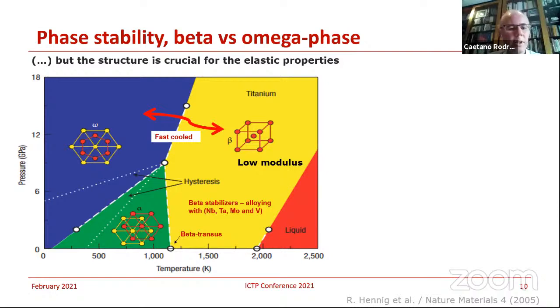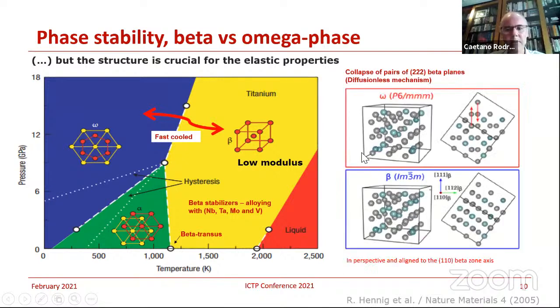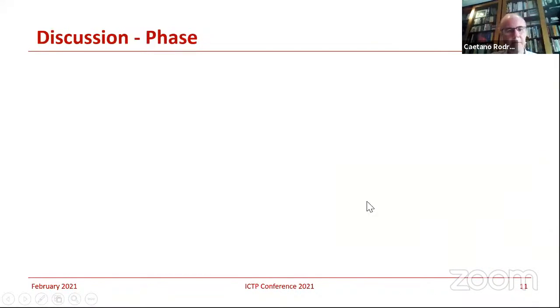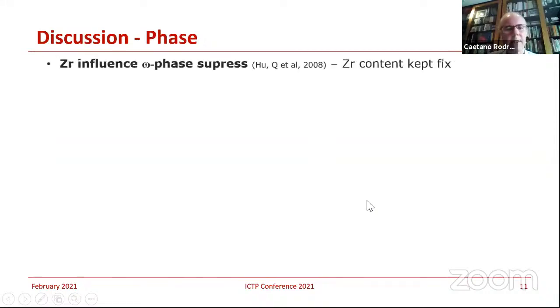Great, yeah. So then you figure out here you get a phase that has a higher modulus. So you have to understand from the thermodynamic point of view, from the elastic point of view, what is going on. So then you have done a series of calculations based on density functional theory to see how is the stability of both phases, the omega and the beta, and also the beta with respect to the alpha one. Now, because of the time, let me just quickly show to you what you have ended up with.